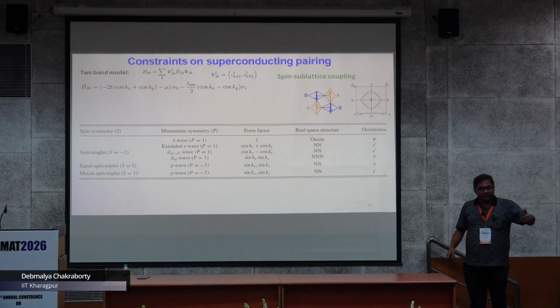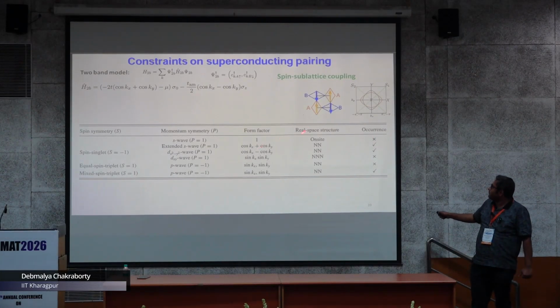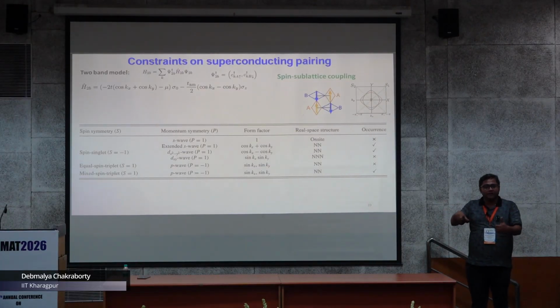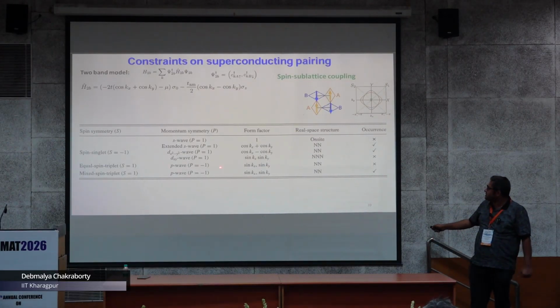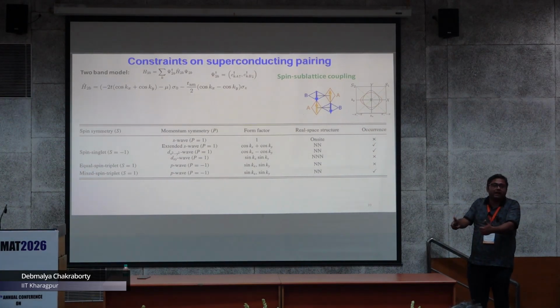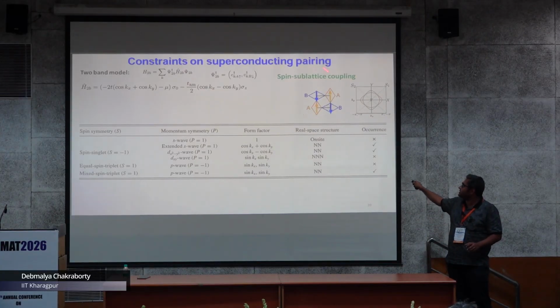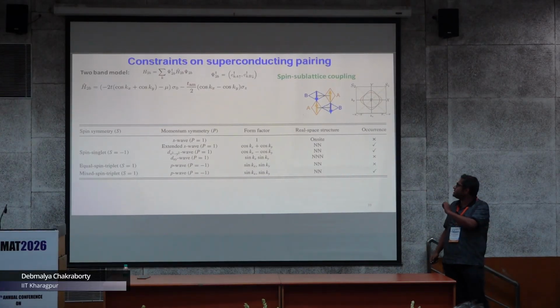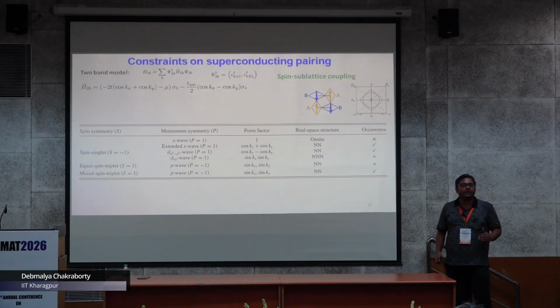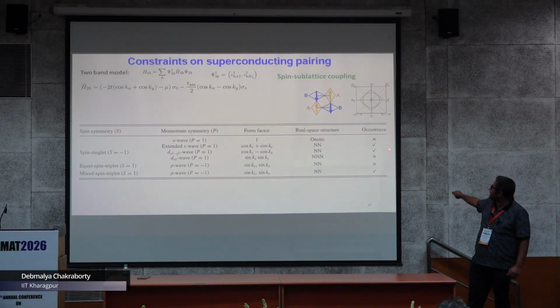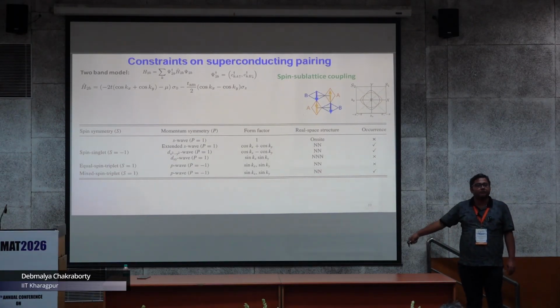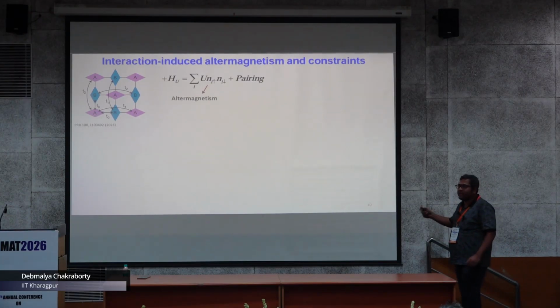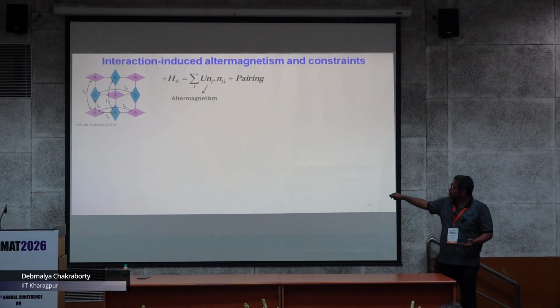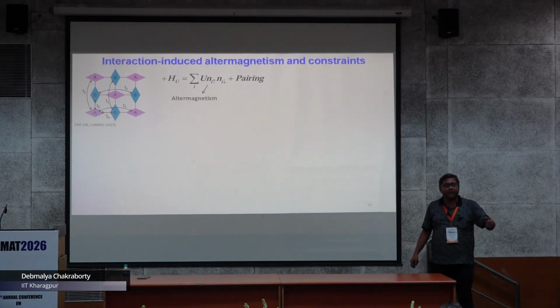Think of triplet, equal spin triplet, that would mean that there is a p-wave pairing, nearest neighbor p-wave, which is this case, and that would need up-up in nearest neighbor, which again cannot happen. As a result, this constraint that the spin and sublattice are locked gives rise to the fact that many of the pairings cannot happen. And as I was saying, the d-wave is one of the highly likely possibilities, which we actually derive to show. So till now I was assuming that there is altermagnetism.